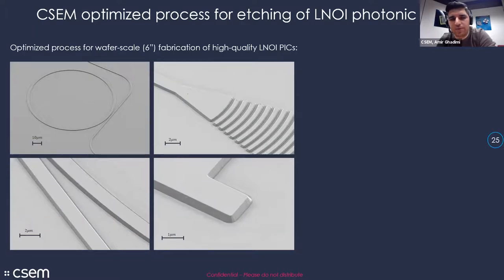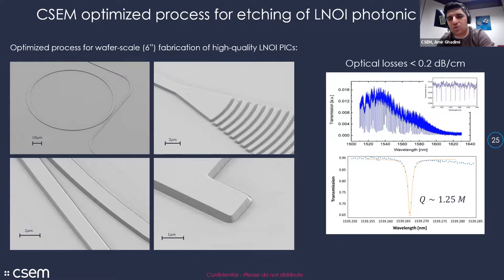For example, this is an SEM. I want to take a moment to appreciate the edge roughness that we can achieve in our process at CSEM. And when you have such a smooth surface, you can actually measure really high Qs. I also show here one of our measurements of one of these cavities that I show on the left. We can very routinely achieve quality factors above 1 million.